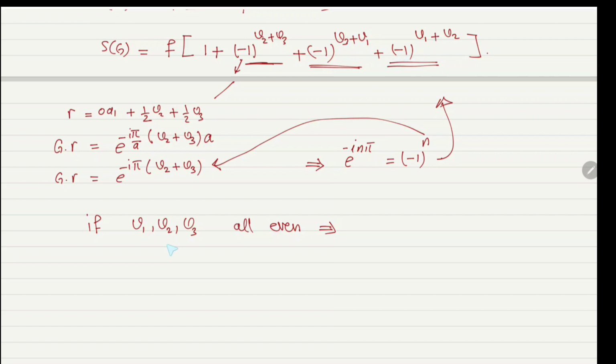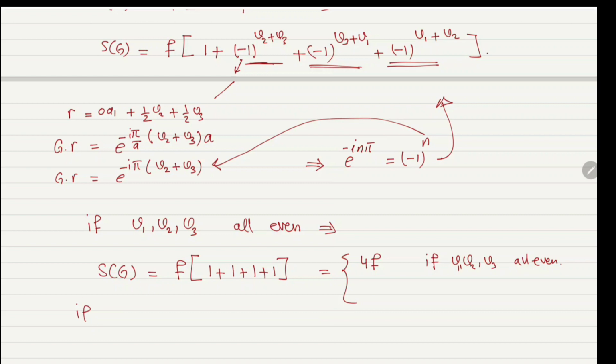In this case, the structure factor is equal to f plus f plus f plus f, or in other words, it's equal to 4f if V1, V2, V3 all even.